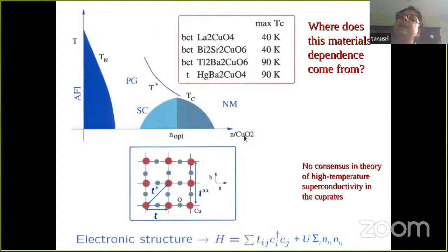This is the phase diagram of the cuprate, which is very well known in this audience. All the copper oxide family basically share the same kind of phase diagram with a dome-shaped superconductivity, with the maximum point of this dome being the Tc at optimal doping, that shows a very large material dependence. For example, in case of the lanthanum cuprate, this Tc is 40 Kelvin, while if you go to the mercury compound, this is more than double, already 90 Kelvin.